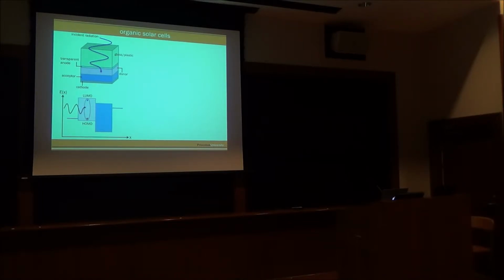And so they're going to migrate around until they find an interface that gives you enough driving force to split the electron hole pair. And when you then split the electron hole pair, your electron can migrate in the acceptor along its LUMO and be collected at the external electrode, and the hole can migrate along the HOMO of the donor and be collected at the external electrode. So now you begin to appreciate why these solar cells aren't very efficient devices. The efficiency of one such device is the compound efficiency of all these different processes. Light absorption needs to be good. This exciton diffusion to the interface needs to be good. Charge transfer to the acceptor needs to be good. And then charge collection needs to be good.